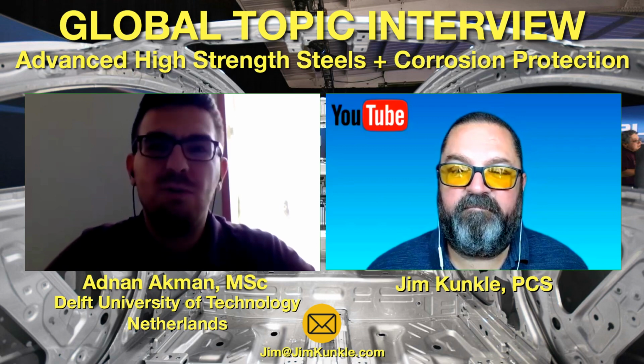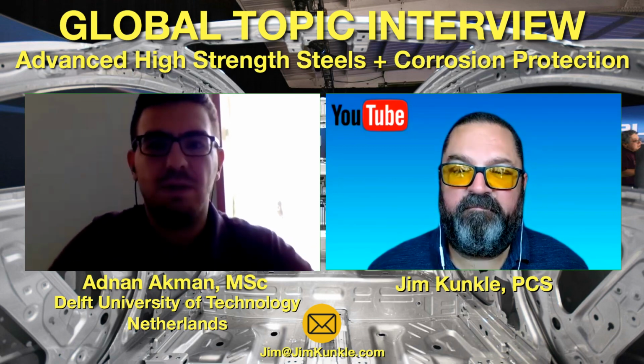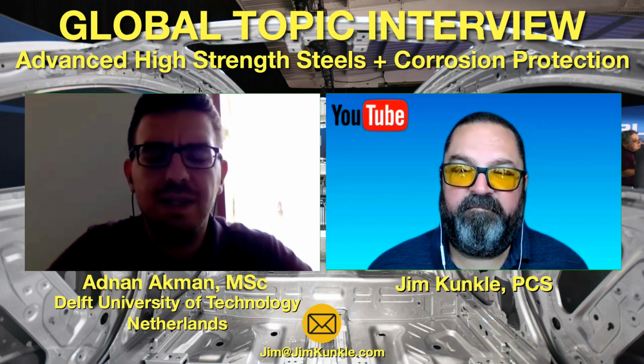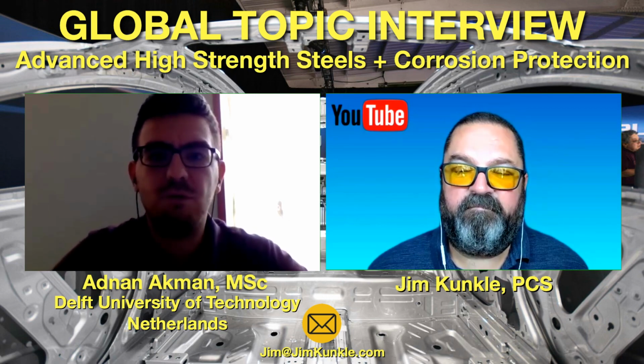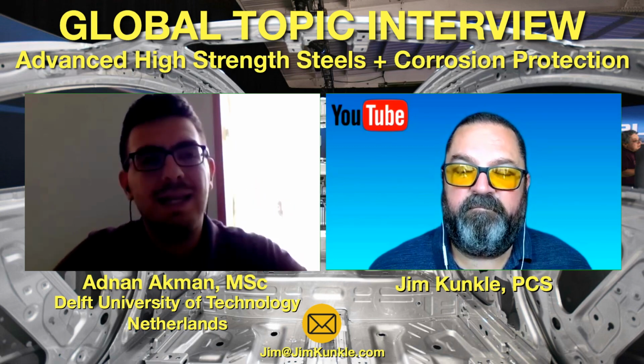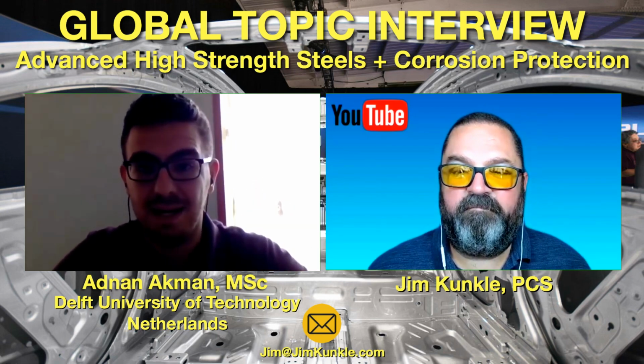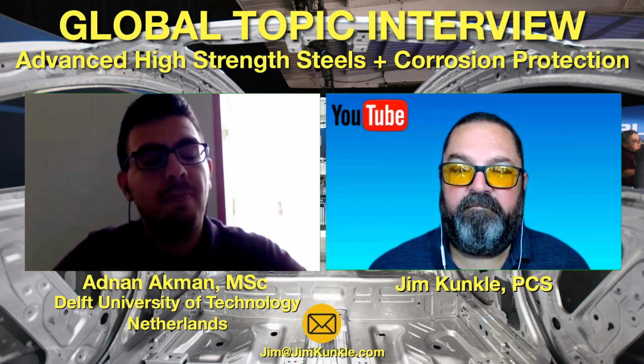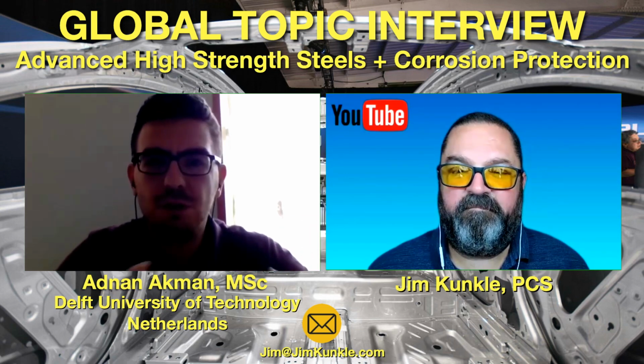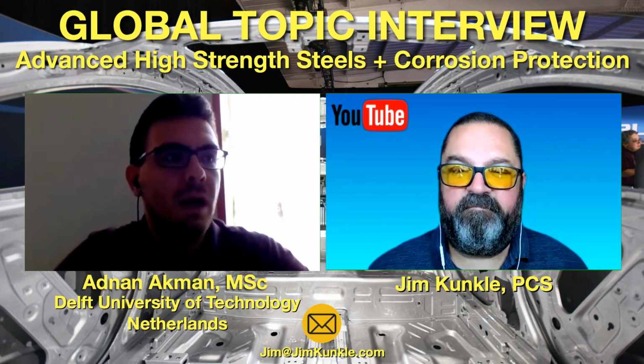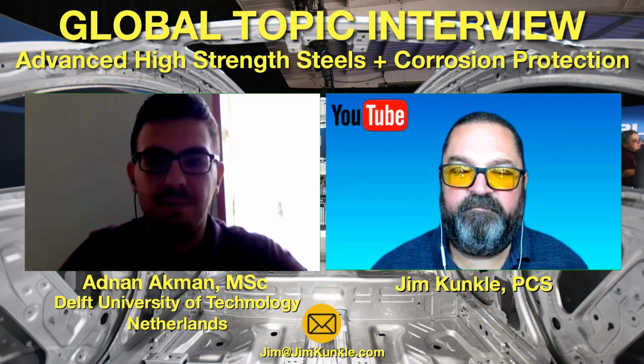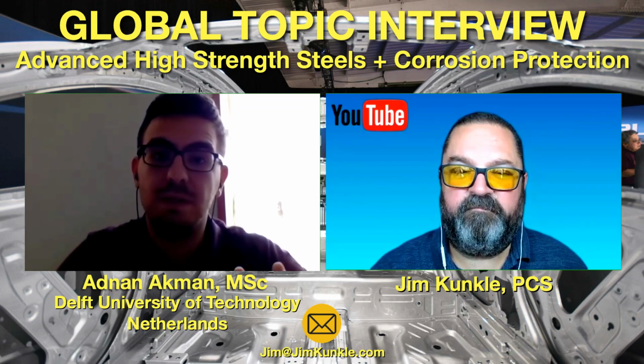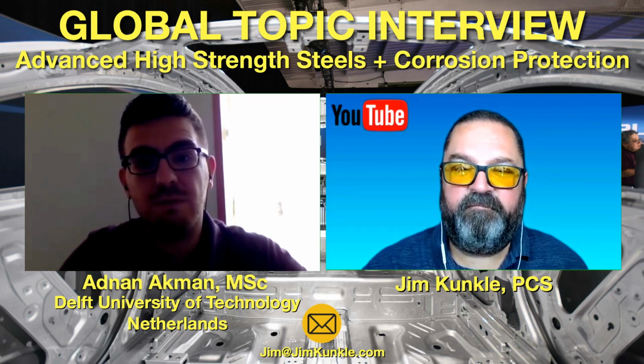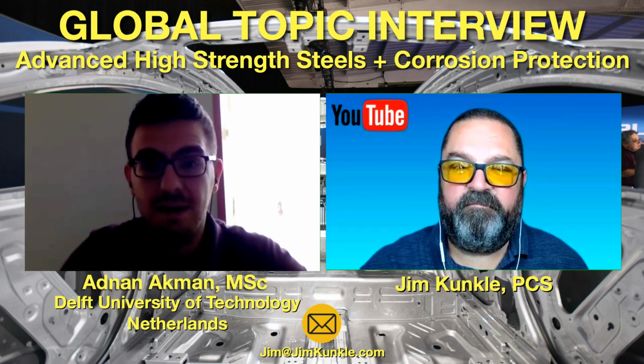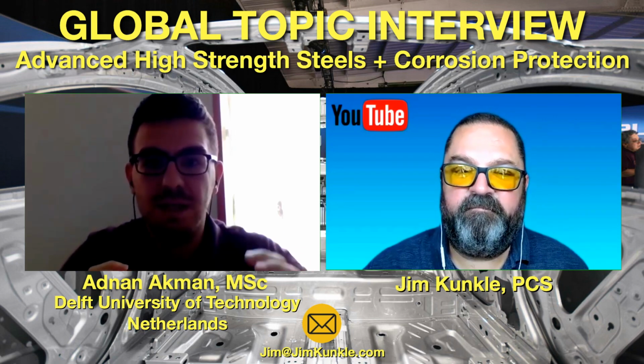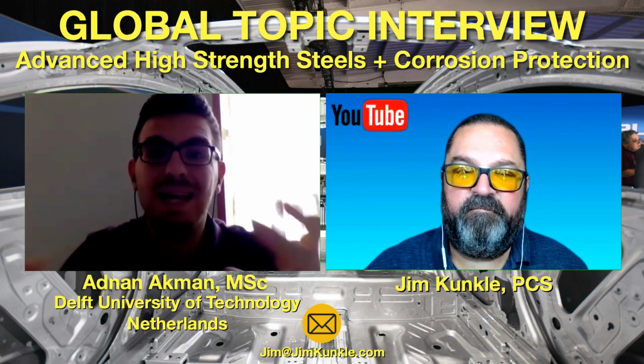For example, I would like to give small information about some specific groups, the most common groups for automotive industry. For example, dual phase steels. As you can understand from its name, it contains two phases, dual. These are ferrite matrix with martensite islands. Martensite is the hardest phase in steel. So if you consider the microstructure, the combination of ferrite and martensite at the same time. But how can we achieve high strength and ductility? You can think basically, ferrite is responsible for ductility, martensite islands are responsible for strength. So by combining different microstructures, I mean kind of microstructural tailoring, you can achieve desired properties.